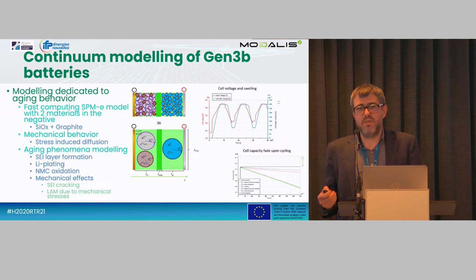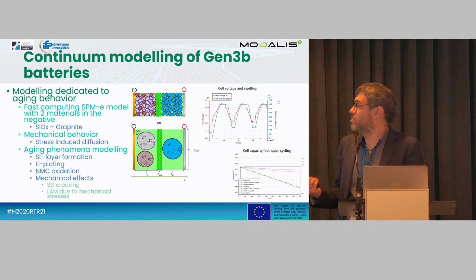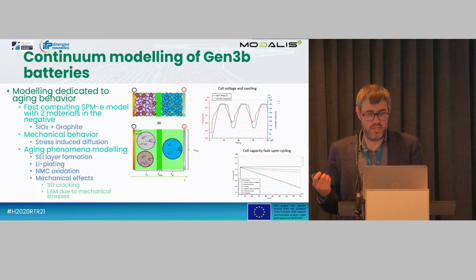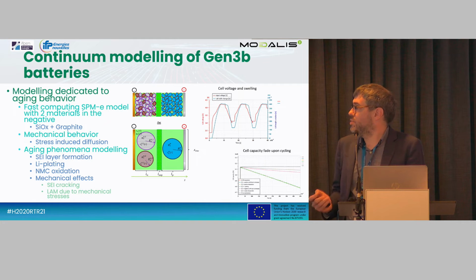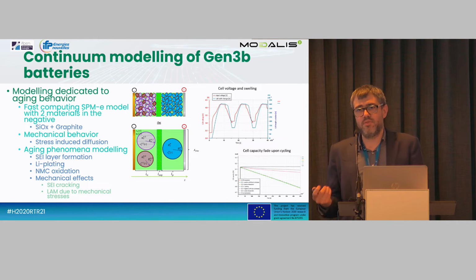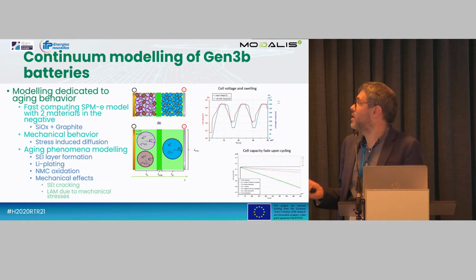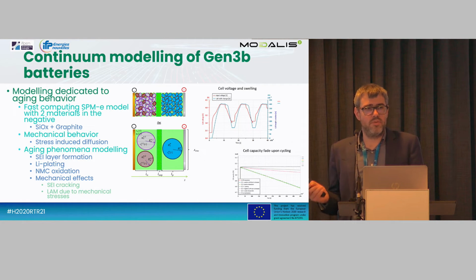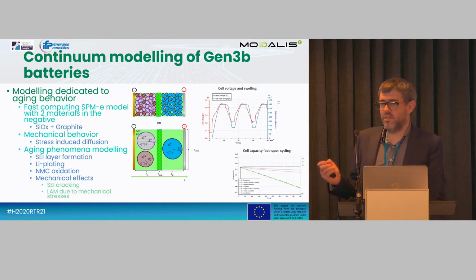Finally, this was implemented into a continuum model, so based on the Newman approach, and simplified Newman approach, which is SPMe, so single particle model with electrolyte. We are able to model the complete system with two particles, one for the graphite, one for the silicon, and take into account the mechanical behavior in terms of nominal working. So when the swelling of the particle occurs, we have a swelling of the whole electrode, so of the whole battery. So we can see how the battery is working and swelling within the system.